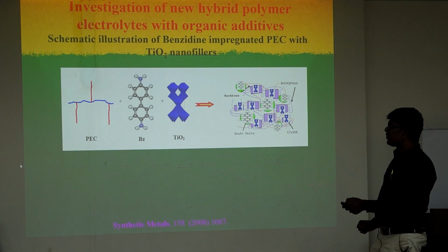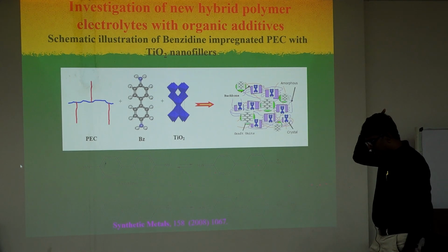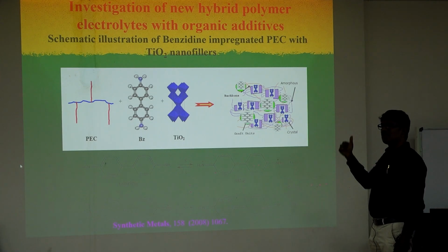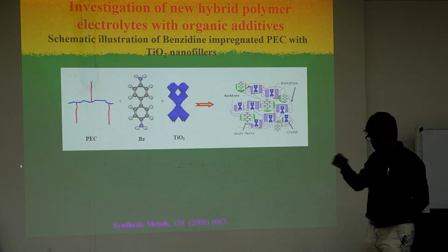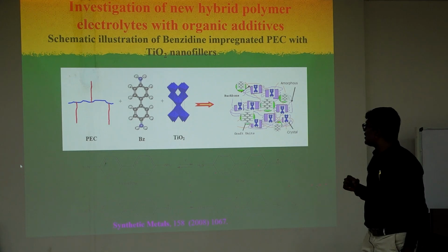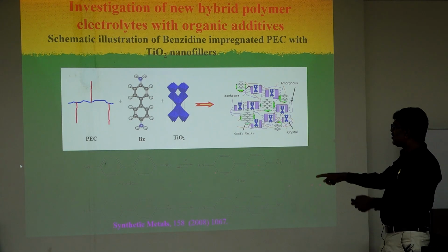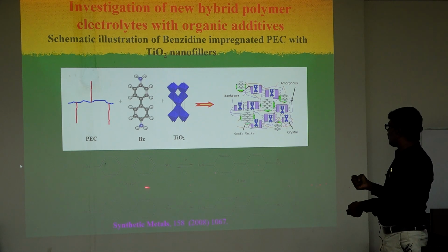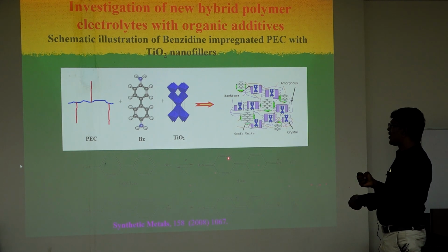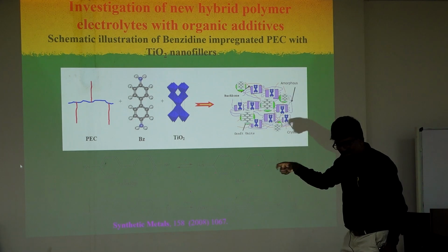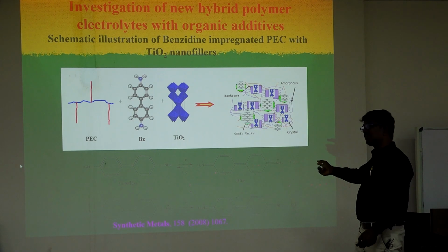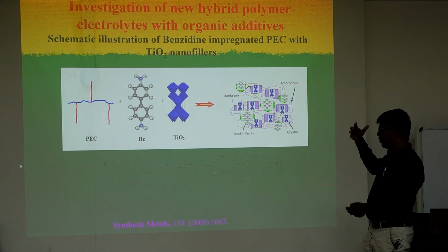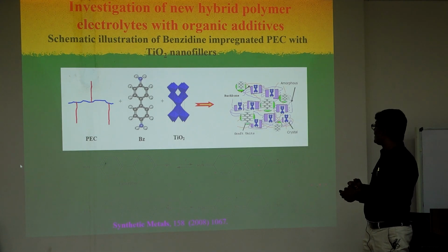So what happens here? I told the preparation of the solar cell, step 2 and step 4, that is the cation coming back to the ground state. So these compounds can avoid that. The benzidine is a colorless compound. When we give the light energy, it forms a radical. It forms a blue radical. So the dye molecule absorbs, and also this forms a radical in situ. So this also absorbs light energy and gives more efficiency. Very important here in this case.